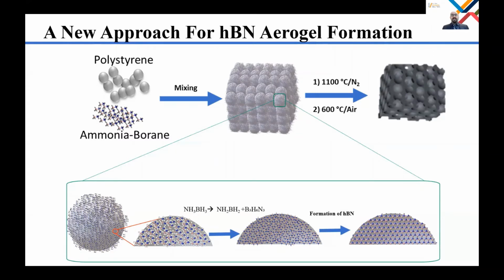High temperature annealing of this hybrid nanocomposite of ammonia borane and polystyrene results in the formation of an aerogel. Here the mechanism is that the molecular ammonia borane adsorbs on the surface of polystyrene nanoparticles and decomposes into aminoborane at around 100 degrees. And around 150 degrees, the structure turns to borazine molecules. Borazine is the main building block for BN synthesis. Here, borazine undergoes dehydrogenation and produces interconnected BN nanosheets on the surface of polystyrene nanoparticles when we increase the temperature to 1100 degrees under nitrogen atmosphere. After we remove the polystyrene nanoparticles by decomposition at 600 degrees under air, the ultra lightweight BN aerogel with interconnected spherical porous structures forms.